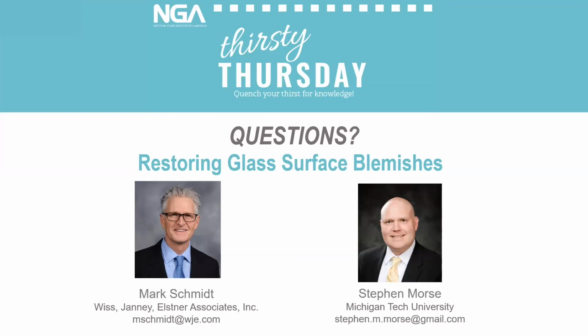It does preclude, in general, the use of the gas, because depending on what the interlayer is, the tin side of the glass is usually not on the number one surface, and so that makes it a little more difficult to measure that. The Scout does not have that limitation. Yeah, I think that addresses that one.